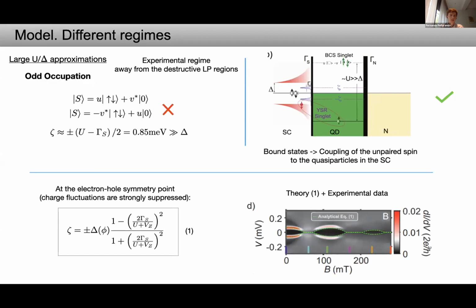So if we take the large U limit in the previously derived formula for the Andreev bound states and evaluate it at the electron-hole symmetric point, we get the following expression for the energies of the subgap Andreev bound states, with dependency on the magnetic field. We can plot this result on top of the experimental data and find very good agreement without additional fitting parameters.